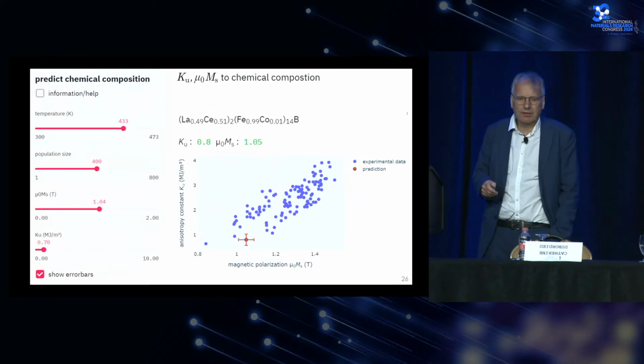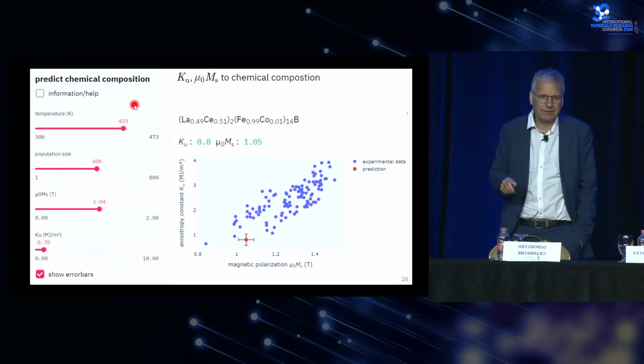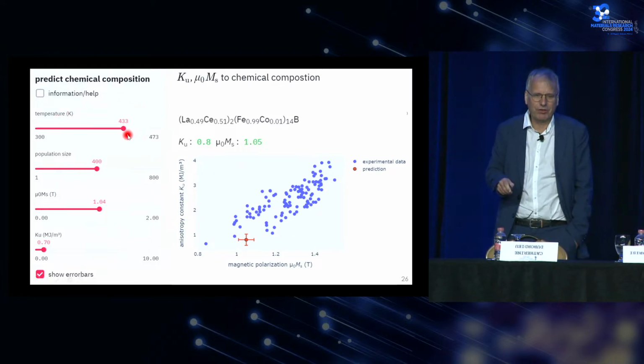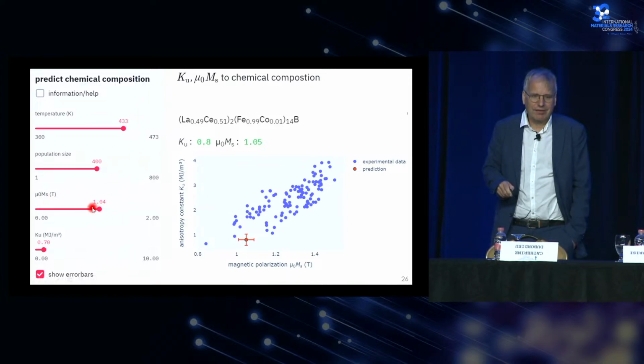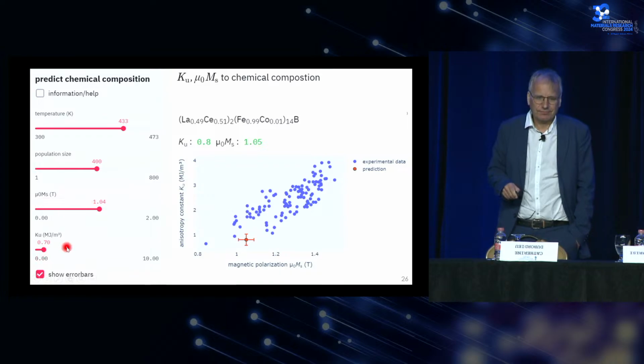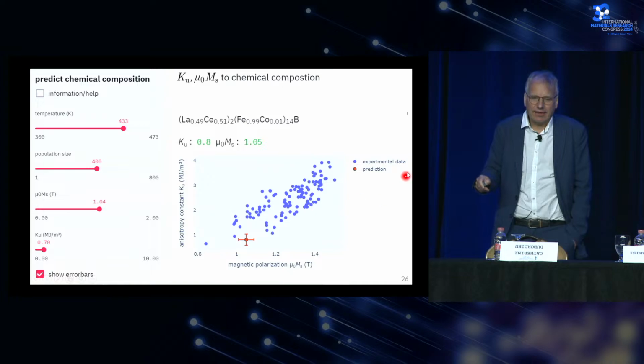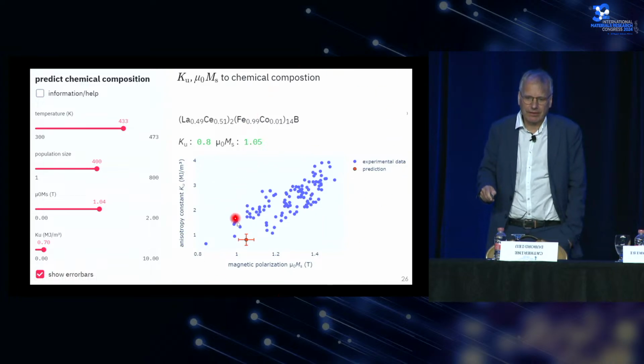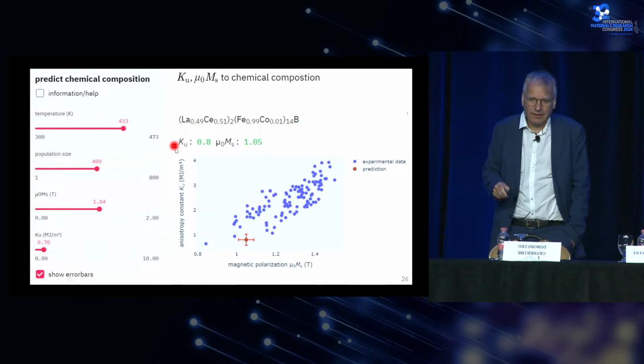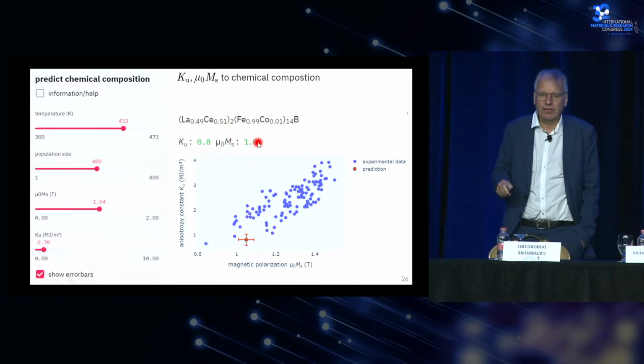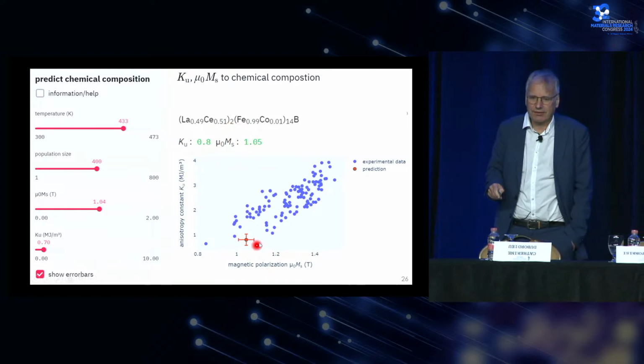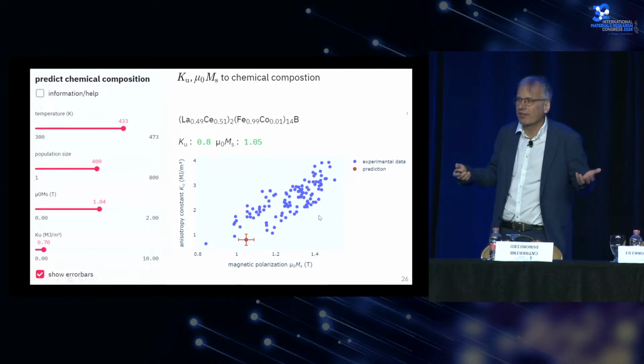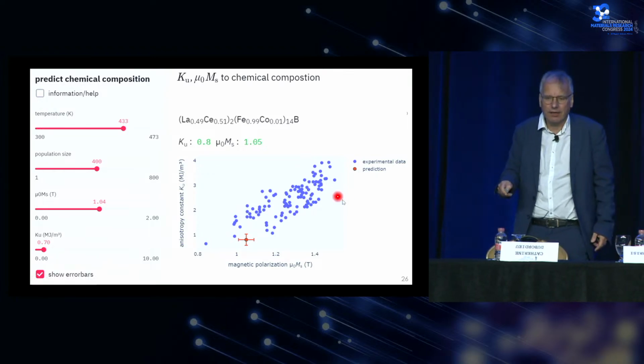So here's an example. We have this tool set where we ask for a certain temperature. We want to have at a certain temperature a certain magnetization, and we want to have a certain anisotropy constant. And then we get as output a certain point with a certain chemical composition and the predicted anisotropy value and magnetization value for this certain point. And you see, we find new chemical compositions that haven't already been in our data set.